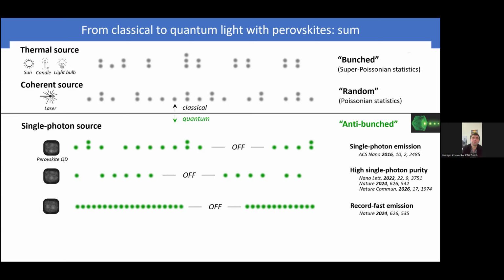There is another very specific problem with perovskites, because lead 2+ is actually quite an electronegative cation. So in some of the devices like light-emitting diodes, when you pass electrons through these, they are much easier to reduce than cadmium 2+, for example, or some other quantum dot material. So it's a bit of an unexpected problem. Or in photoredox applications, when you use it as a photocatalyst, you can actually self-reduce the quantum dot with electrons. So you need to do a more balanced charge injection in the case of LEDs, or have some sort of hole and electron balance when you do photoredox.